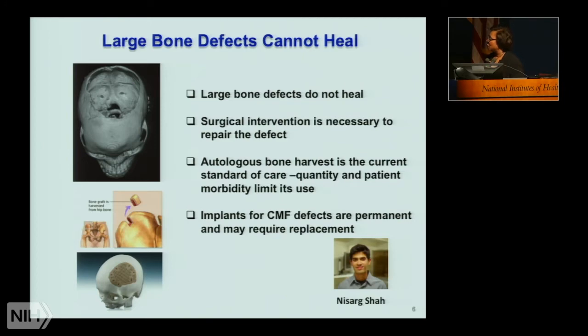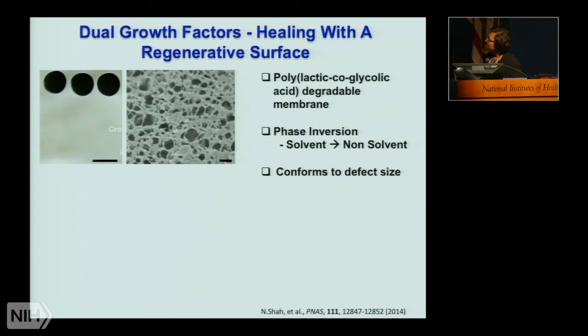There are also problems with other approaches. We can look at other materials that can cover or essentially protect this area, but then we have an issue with the material interface that is generated as a result of that. So we decided to investigate the release of growth factors with very small doses over a very controlled time period from a scaffold that degrades. And to do this, we started with PLGA, which is a known FDA-approved polymer, and we generated porous membranes from them using a very simple processing technique. So these end up feeling like white, soft, floppy films that you can cut out with a cookie cutter, which was done here.